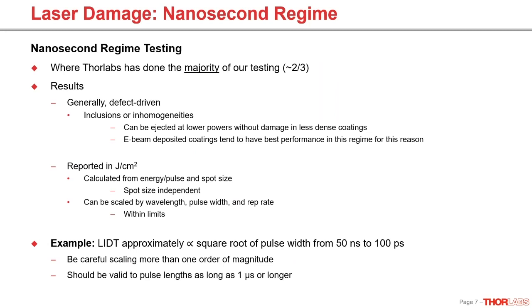And for a reasonably large spot size, this should be relatively spot size independent, assuming you're at probably at least 100, 200 microns. And this can be scaled with wavelength, pulse width, and with rep rate, obviously within limits, which we're going to be getting to later in the presentation. So just as an example, damage threshold scales approximately with the square root of pulse width from 50 nanoseconds to about 100 picoseconds. And you typically don't want to scale more than one order of magnitude there, but this can be used just to give you a ballpark idea of what to expect. And this can be valid potentially up to a microsecond, but we try and stay in the region laid out there.